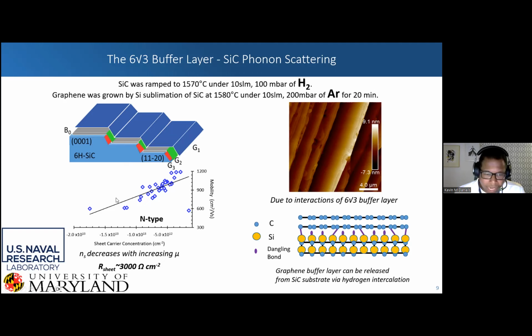One thing that's not shown here is that you do have pretty high temperature dependence. If you heat up the material, your carrier mobility will go down pretty quickly. If you cool it down, it will go up pretty quickly. And the material is N-type.